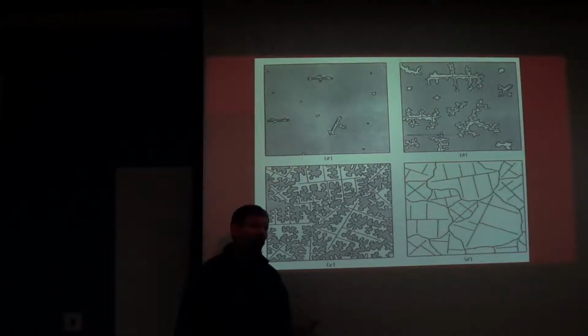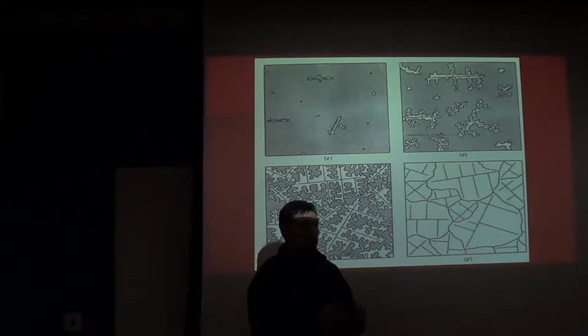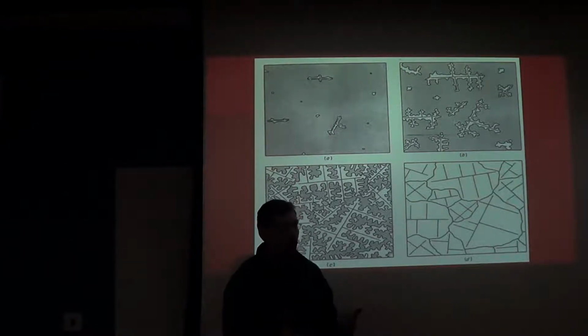The carbides are pretty hard. They are actually physically hard. And so they're not going to deform in the same way that the surrounding iron matrix will. And so now you get a difference in what's called flow stresses. As you try to deform this, the carbide is maybe pushing through the softer iron matrix, perhaps creating some shear stresses at that interface, and resulting in a tendency for this to want to come apart during deformation.